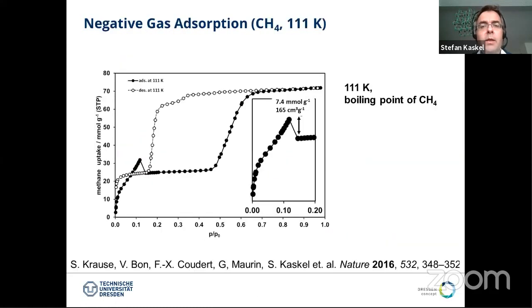And therefore, we did something which is maybe not so standard. We went to the boiling point of methane, which is 111 Kelvin, and recorded a normal isotherm like you would do for nitrogen. And we found a very strange behavior. So this material has a kink in the adsorption branch. And basically you adsorb some gas and then suddenly there's a step here and a plateau. And this step here, you can think, oh, maybe it's just an artifact, but it's quite high.